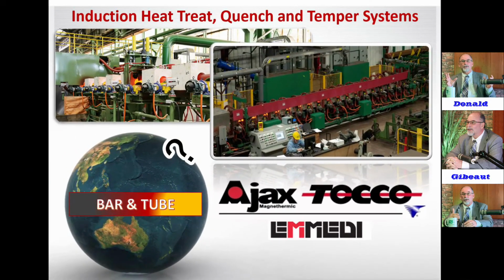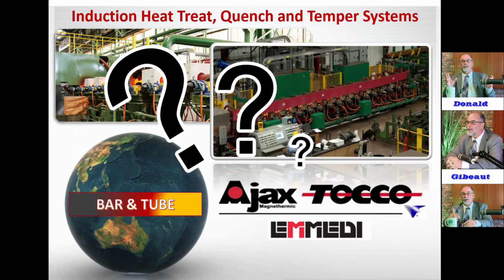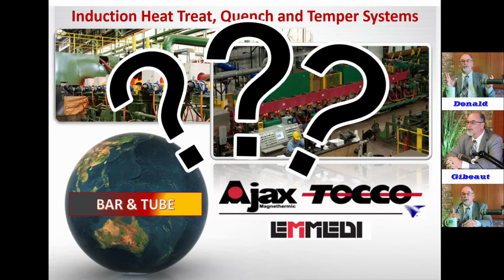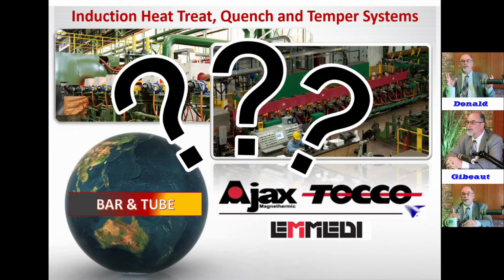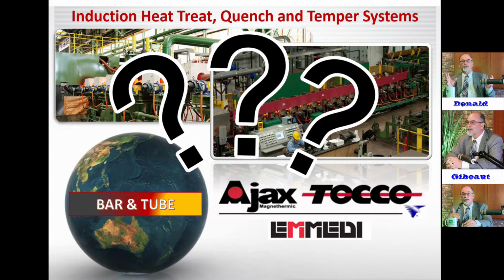So back to your question, is this process suitable for all API steel grades? We do L80 and P110, which is the more difficult API grades. There's different temperatures, there's different feed rates. Which holding time at constant T can you have on the tempering furnace? To homogenize the temperature on section and on the length. That comes into a question on the temper. You know, it's below the magnetic Curie, so the reference depth of penetration is shallower. So versus the austenitized side, your delta T is broader.